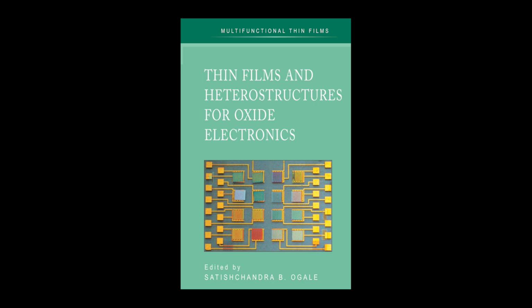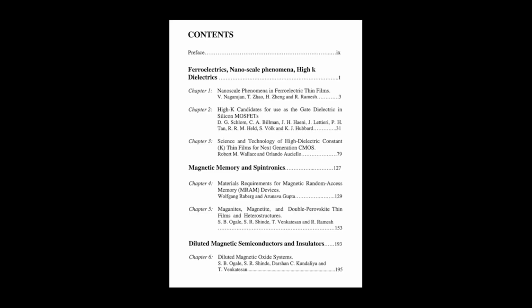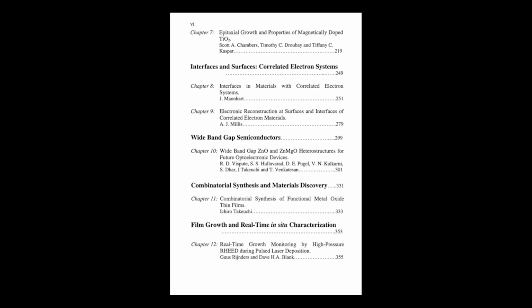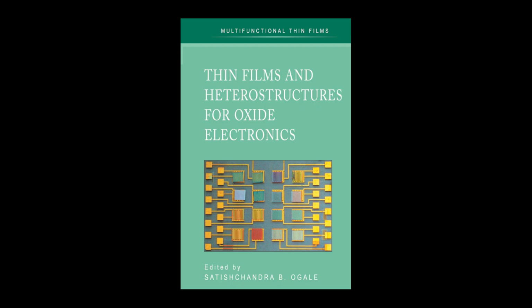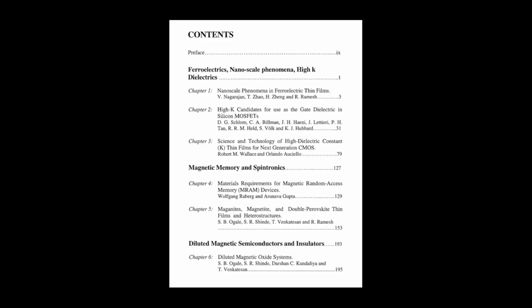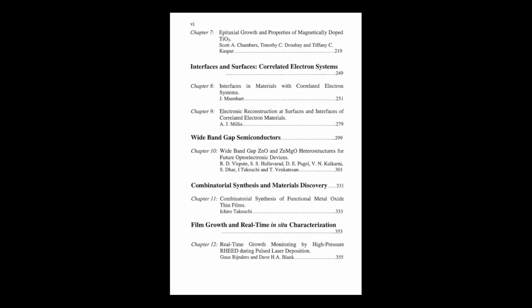But the problem is, many complex oxides, especially when grown by PLD, need a significant background pressure of oxygen to get the stoichiometry right. And RHEED uses an electron beam. And high-energy electrons scatter like crazy off gas molecules. So standard RHEED just doesn't work at the oxygen pressures needed for growing many oxides, which could be up to, say, 50 Pascal. That's way too high for a normal electron beam. A fundamental conflict. How did they solve it? How do you get RHEED to work at high pressure?